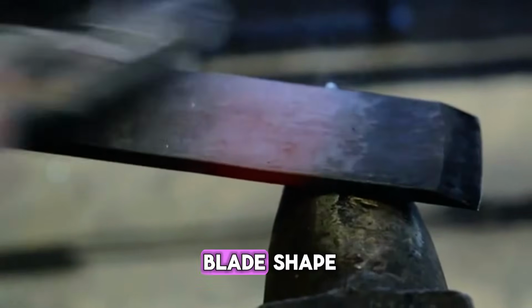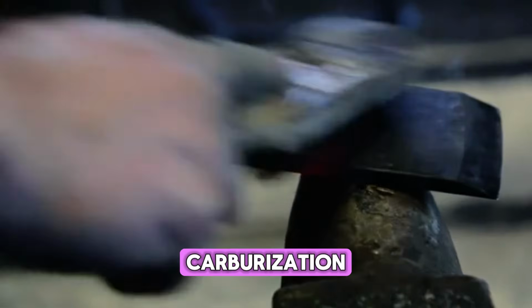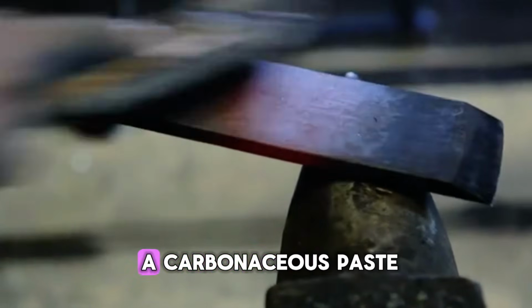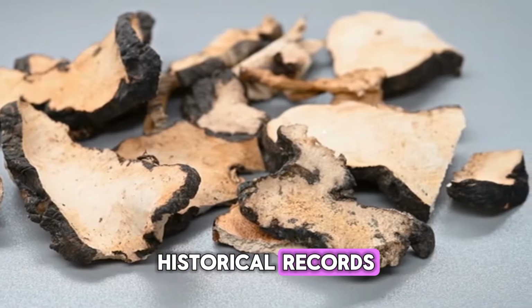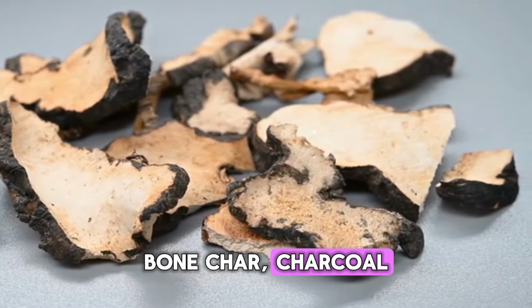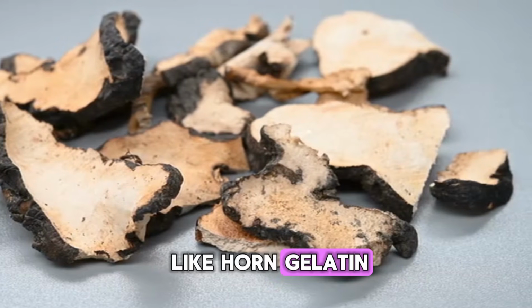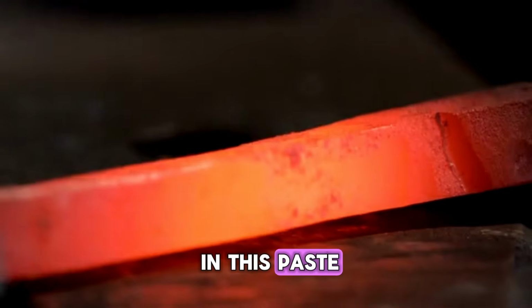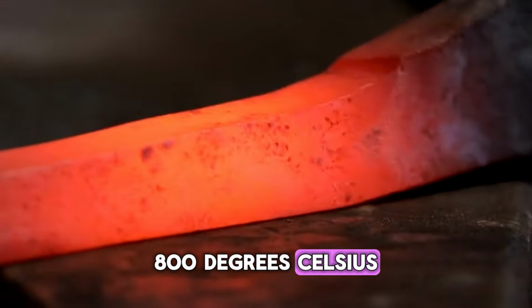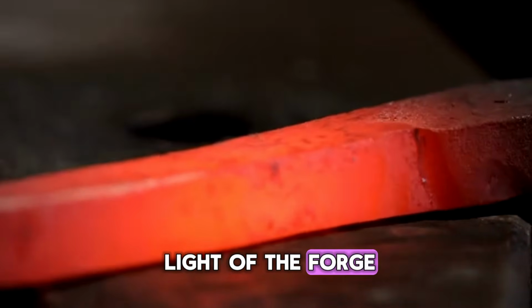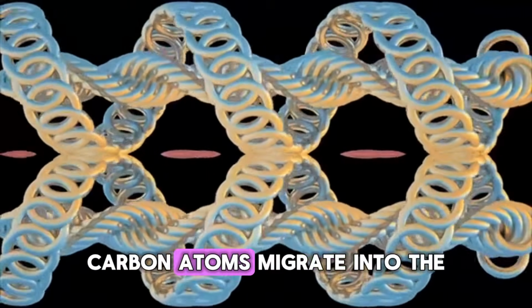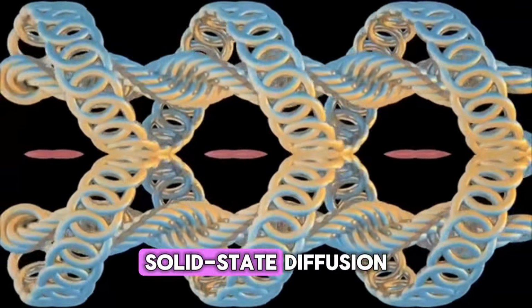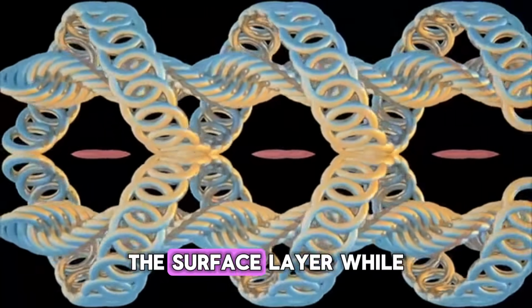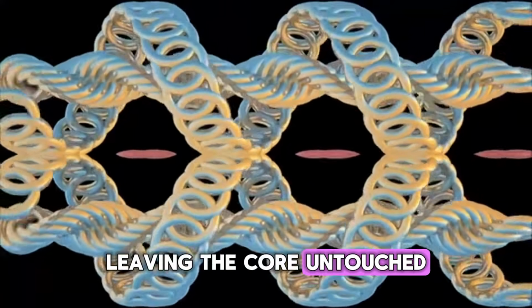After forging the basic blade shape, Roman smiths employed selective carburization, deliberately packing the cutting edge in a carbonaceous paste. Historical records describe mixtures containing bone char, charcoal, and even animal matter like horn gelatin. The blade edge, coated in this paste, was heated to temperatures exceeding 800 degrees Celsius, cherry red in the dim light of the forge. At this temperature, carbon atoms migrate into the iron's crystal lattice through solid-state diffusion, enriching only the surface layer while leaving the core untouched. They'd maintain this temperature for hours, long enough for carbon to penetrate maybe half a millimeter deep.